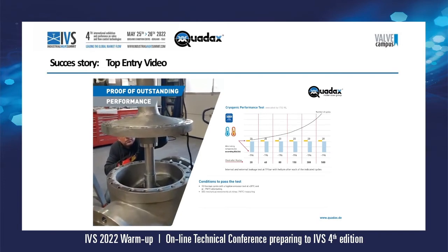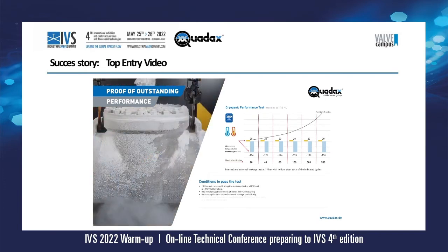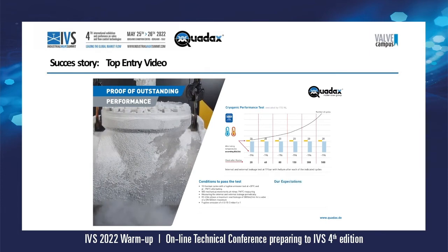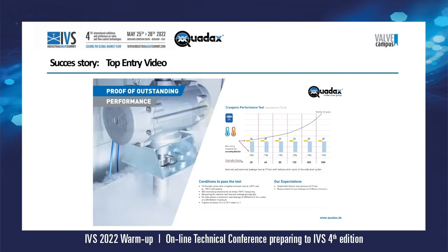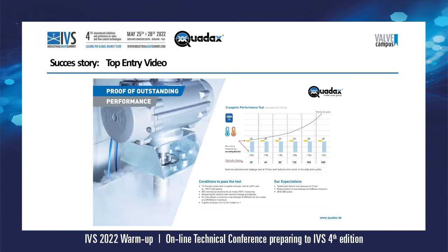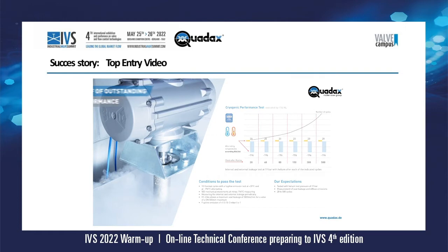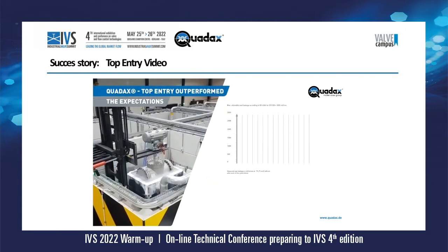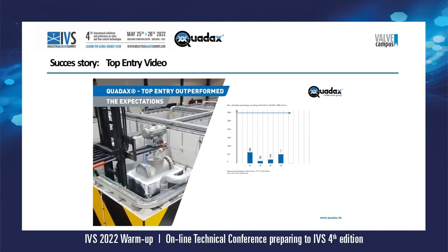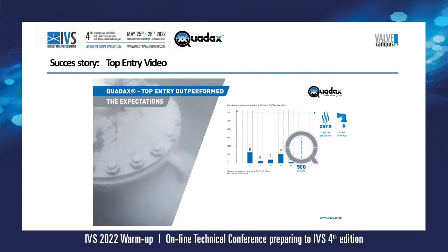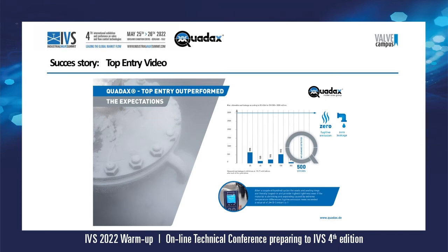The end user stipulated a test with 10 thermal cycles, combined with an endurance test with 500 mechanical switches. To meet this requirement, a Quadax 4-offset butterfly valve with the specifications DN 500mm and Class 150 was tested at the ITIS test laboratory in the Netherlands. The Test Institute ITIS BV certified that the seat leakage never exceeded the low value of 590 milliliters per minute, and after 500 cycles, zero leakage at all was detected. The fugitive emissions were well below the norm and hardly measurable.